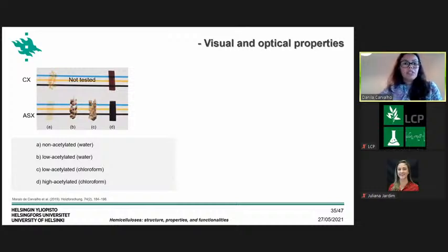The results that we got are here in this figure. Just to explain what we have here, A is the non-acetylated xylan films. And as I told you, we tested without and with plasticizer. Since the results were quite similar in terms of visual aspect, here is just the picture of one of these. In this case, it was the film formed without the use of any plasticizer, but the aspect of the others was quite similar. Then we have in B the xylan prepared at low degree of acetylation cast in water, and C the low acetylated cast in chloroform, and finally the films cast in chloroform using the highly acetylated xylan.